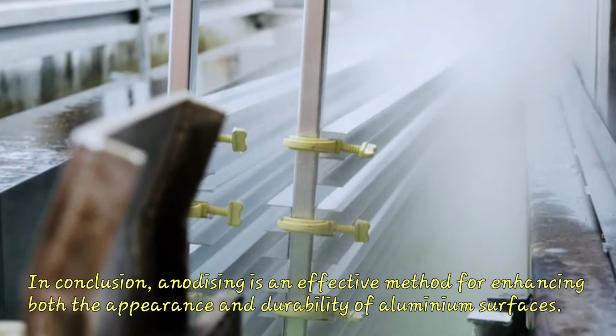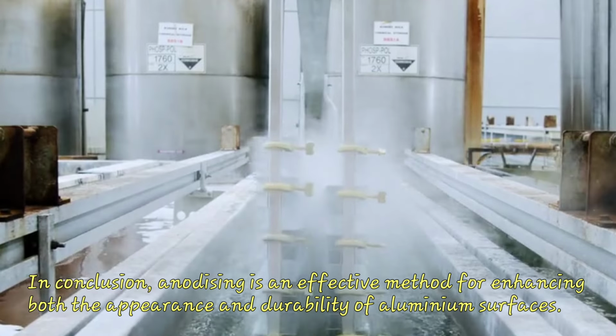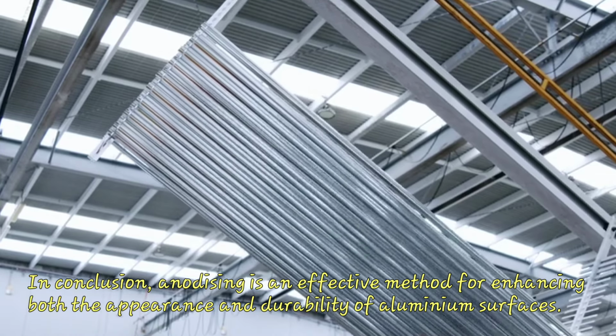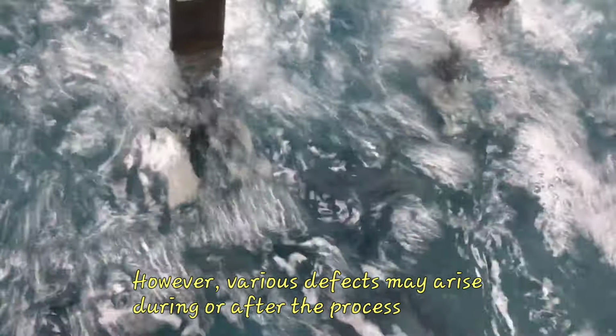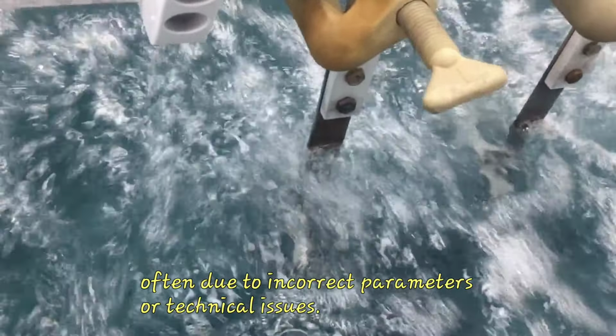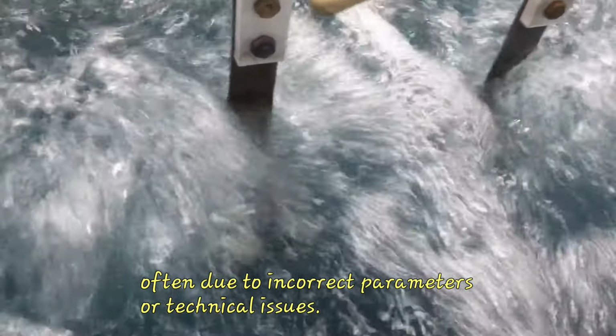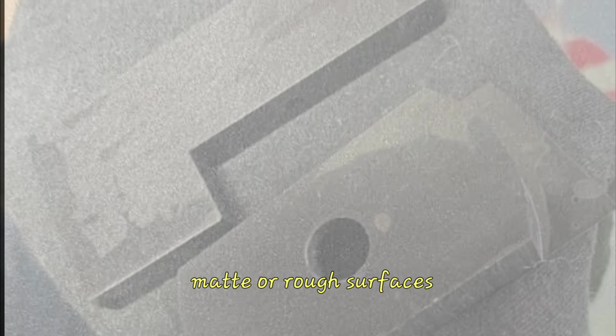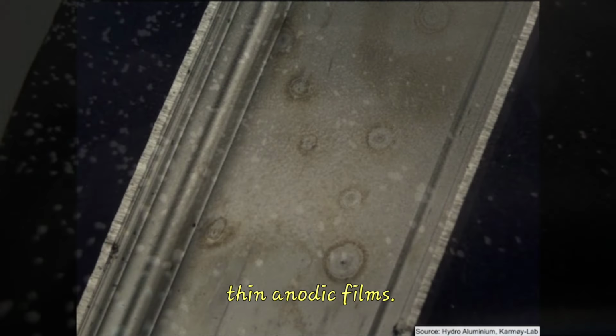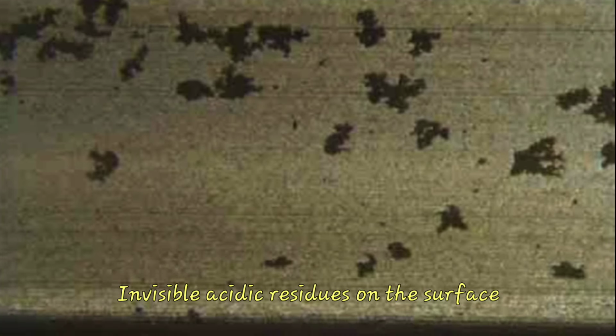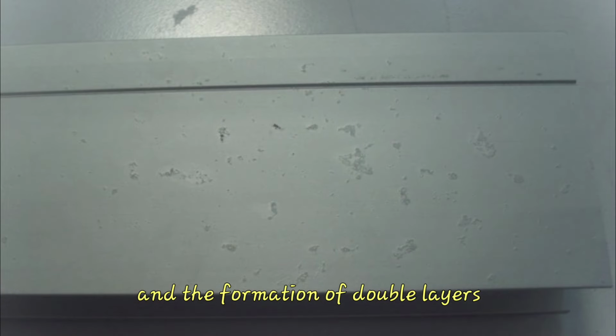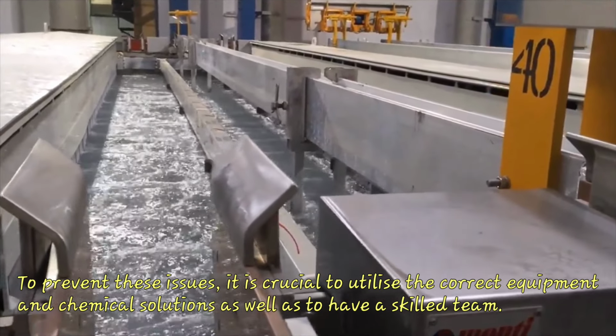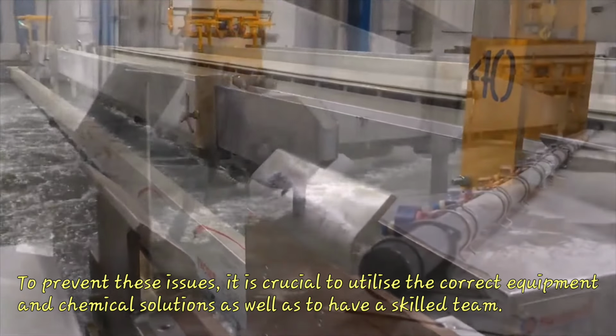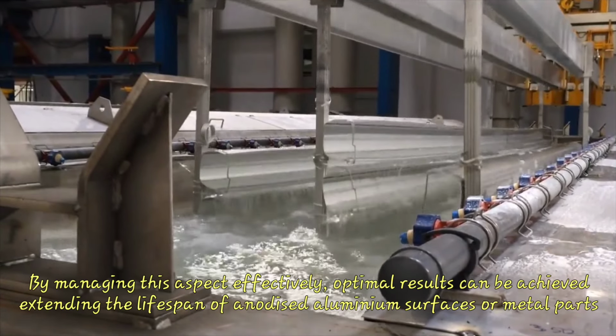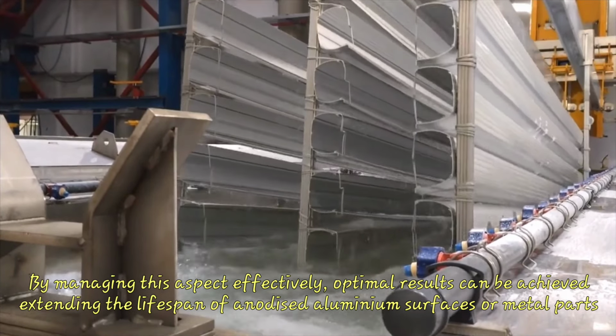In conclusion, anodizing is an effective method for enhancing both the appearance and durability of aluminium surfaces. However, various defects may arise during or after the process, often due to incorrect parameters or technical issues. Common defects include matte or rough surfaces, uneven coloring, cracks or peeling, thin anodic films, invisible acidic residues on the surface, and the formation of double layers. To prevent these issues, it is crucial to utilize the correct equipment and chemical solutions, as well as to have a skilled team. By managing these aspects effectively, optimal results can be achieved, extending the lifespan of anodized aluminium surfaces